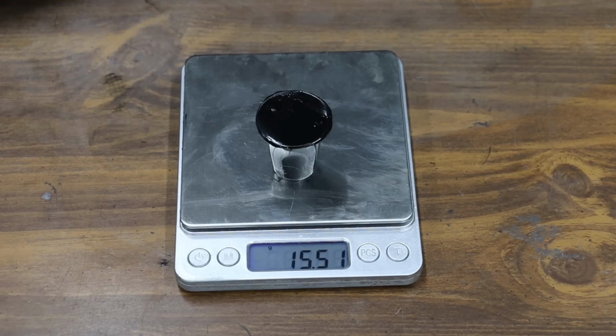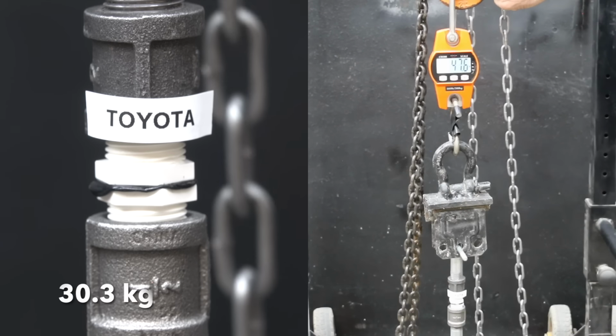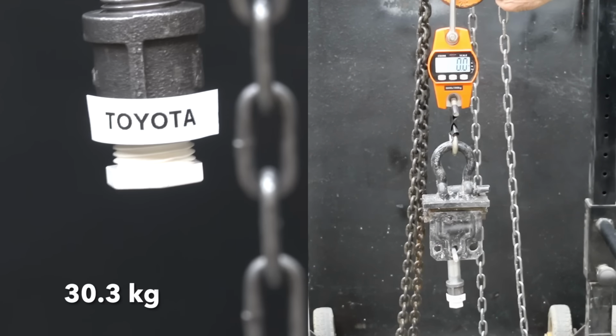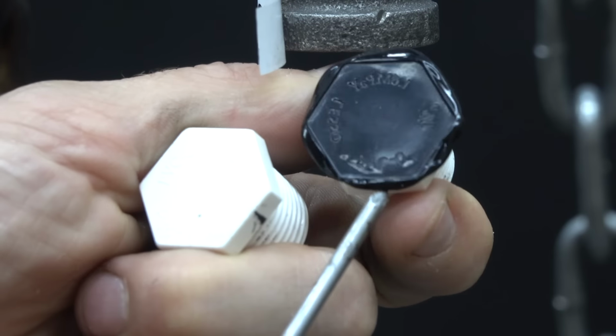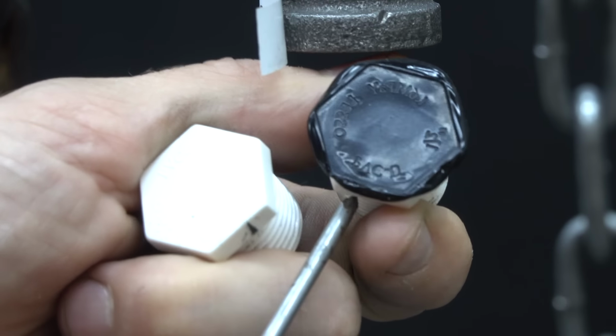And the Toyota weighs very close to the same as the AISIN at 15.51 grams. And the Toyota gasket maker is outperforming the AISIN gasket maker at 66.8 pounds. And the Toyota is fully cured across the entire area of the PVC end cap.